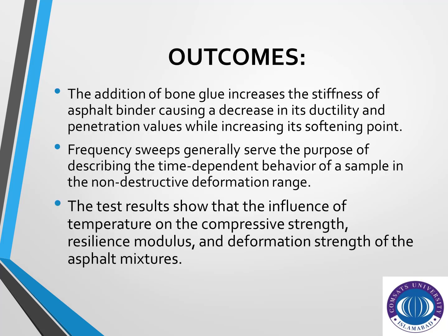Here is the outcome. The addition of bone glue increases the stiffness of asphalt binder, causing a decrease in its ductility and penetration value while increasing its softening point. The tests show the behavior of the material and indicate that it is going to behave well as a good modifier.